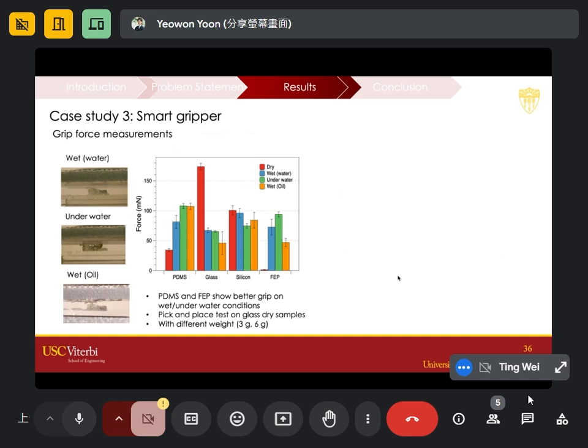So here we did a few tests on different surfaces and different environments. We tested on three different environments, including a dry surface, just open air, and then a wet condition with both water and oil, to see how it reacts on the different types of surface, and then a completely underwater surface. It looks like glass is best with the dry surface, whereas PDMS and FEP film, which have very poor adhesion to any type of polymer, act better in those wet environments.